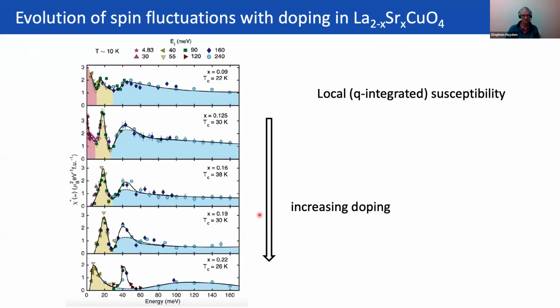This is the spectrum of the whole thing, just around half for different dopings. So you can see these three contributions. This is the sort of high energy spin waves, the blue, and then this peak here is the incommensurate peaks that I just showed you, which you see for many dopings. And then for some dopings, you also see spin freezing for the underdoped side, and that's the pink stuff here. So this peak here is the incommensurate peaks at low energy.